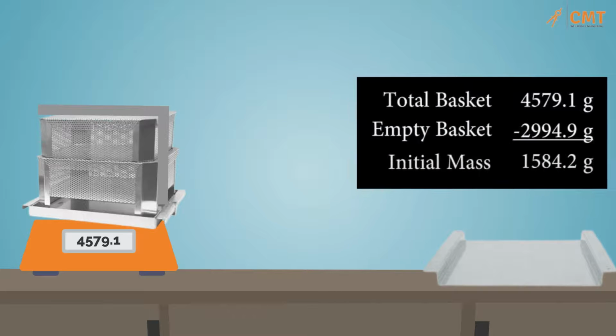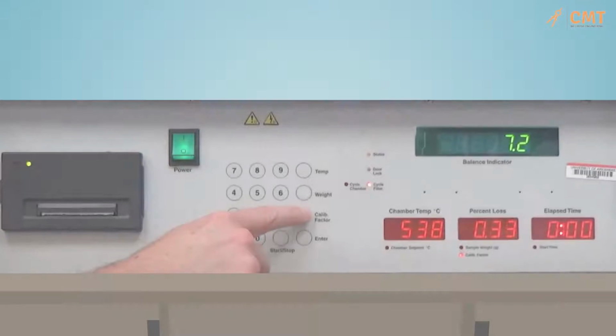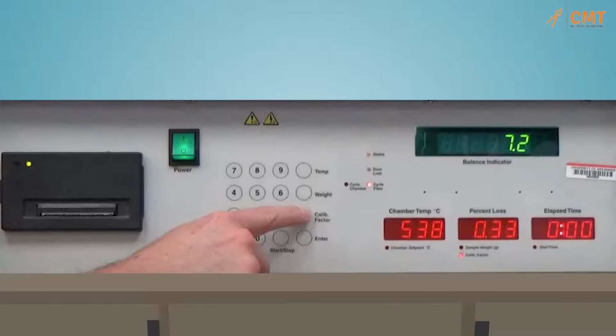Next, you will determine the initial mass of the sample by subtracting the mass of the empty basket assembly from the total mass of basket assembly and sample. Then round the initial mass of the sample to the nearest 1 gram. Input the binder calibration factor by pressing the calib factor button, and then quickly entering the value and pressing enter. The decimal is automatic, so a value of 0.18 would be entered as 18.